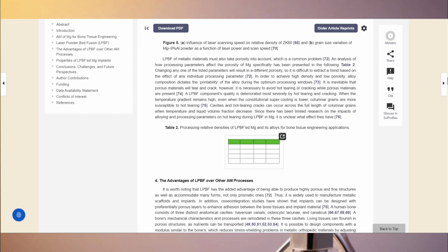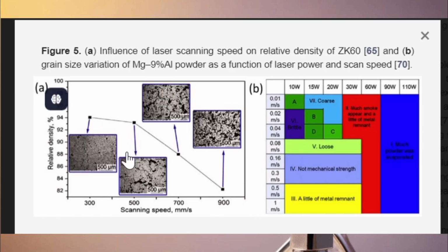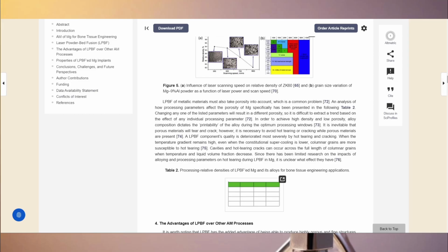Key considerations for bone implant applications. Figure 5 highlights how adjusting laser parameters influences the density and grain structures of magnesium alloys. On the left, A, you can see that scanning speed can significantly affect the relative density of ZK60. Too fast and you risk lower density, of course, as shown in the micrographs. On the right, B, different laser power and scan speeds can lead to varying grain sizes in the Mg, in Mg 9% Al powder specifically. Each color-coded region suggests an operational window. Too low or too high and you might end up with brittle parts, poor mechanical strength, or excessive material evaporation, of course.